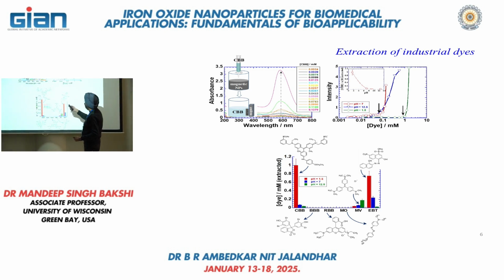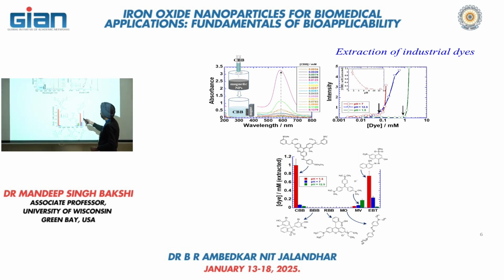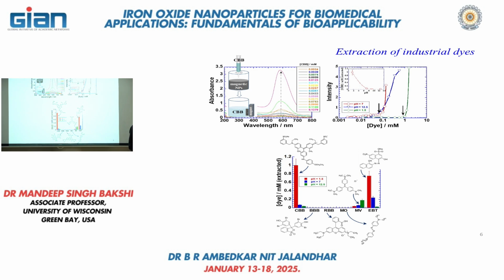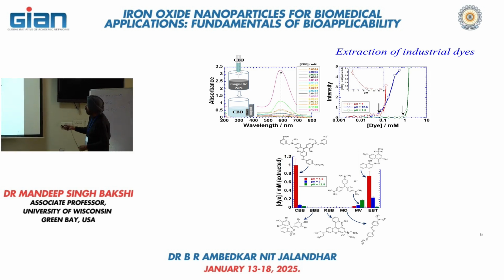Though there is one more over here, but this addition represents this much concentration. After this, there is a bright green, and eventually this is it. It means that the end point has come over here. It is 0.08 millimolar of the brilliant blue dye. So this is the brilliant blue dye solution, and this is the concentration. The end point of this titration is somewhere over here.